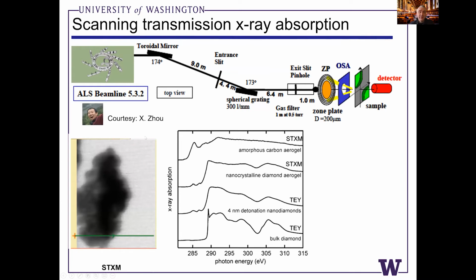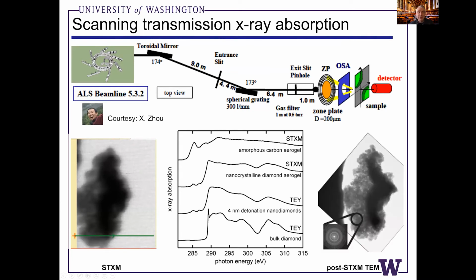I also wanted to share, we've done some X-ray absorption spectroscopy measurements. This is a really terrific user facility at the Advanced Light Source at UC Berkeley, Beamline 532. And we've looked at the amorphous carbon aerogel X-ray absorption spectrum. You can see really pronounced 1s to pi star transitions that indicate graphite or graphitic carbon at about 285 electron volts. The diamond material that we recover has a dip in its electronic density of states at about 302 electron volts that maps onto detonation nanodiamonds.